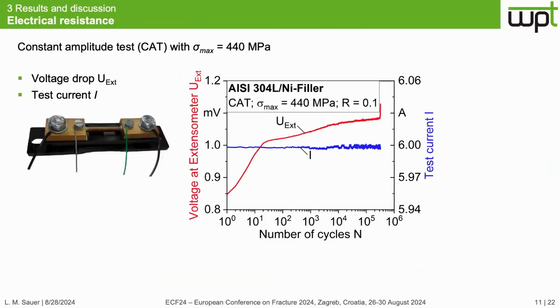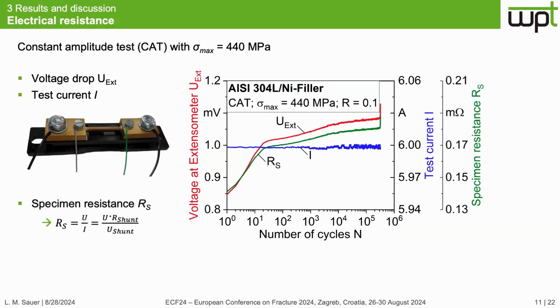I will now show the evaluation on a constant amplitude test with a maximum stress of 440 megapascal. From the voltage drop at the extensometer and the test current measured at the shunt, the electrical resistance was determined by using Ohm's law. And during the fatigue test, there's a significant increase of the electrical resistance.